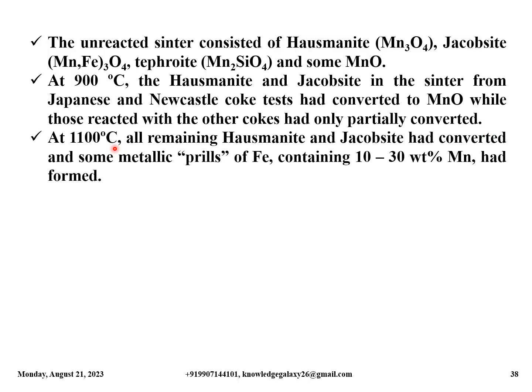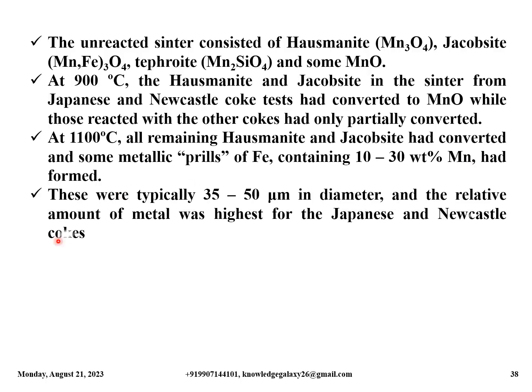At 1100 degrees Celsius, all remaining hausmannite and jacobsite had converted, and some metallic prills of iron containing 10 to 30% manganese had formed. These were typically 35 to 50 micrometers in diameter, and the relative amount of metal was highest for the Japanese and Newcastle cokes.